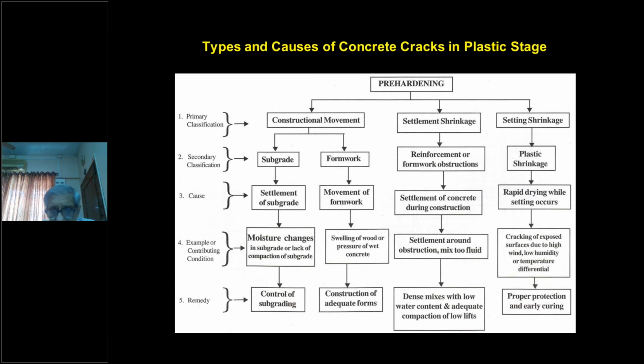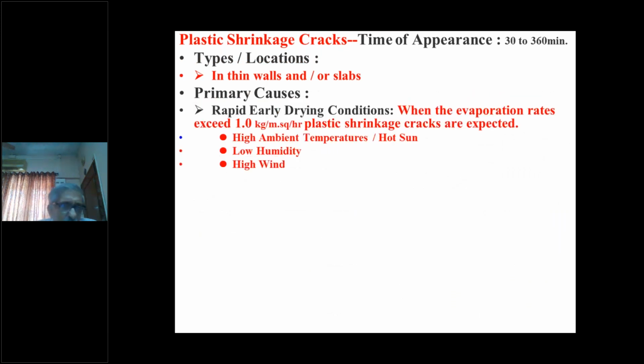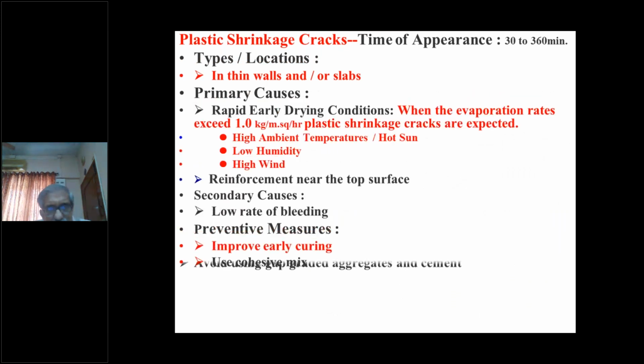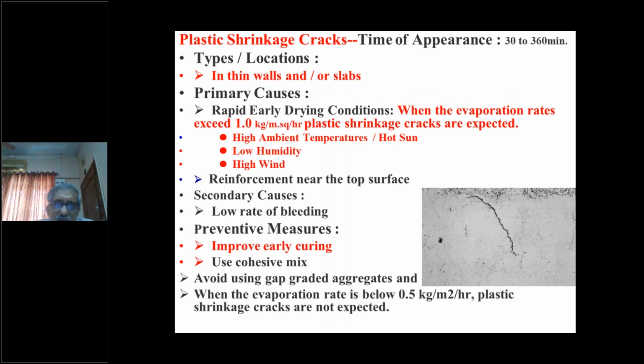Many a time people do curing by several methods, sometimes totally inadequate methods, which I'll be showing you, and the slab develops cracks. And mind you, concrete is very young at that time, so these are through and through cracks. So very easily it will allow the rainwater to seep in. We do deal with the plastic shrinkage cracks in a little more detail. Mind you, they occur within 30 to 360 minutes. It may take a little longer or even a shorter time.